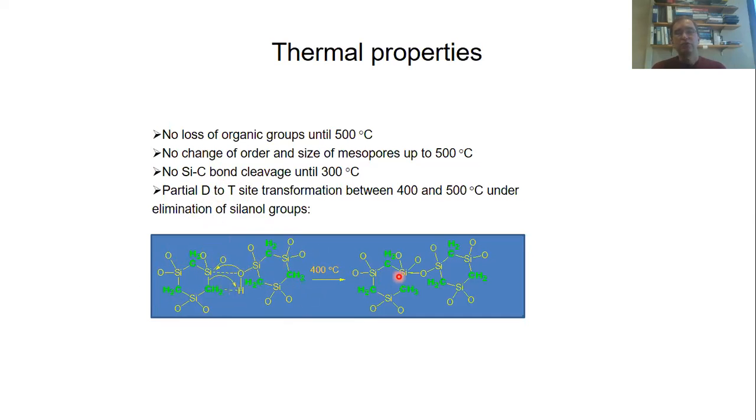So that can actually form a silicon-oxygen-silicon bridge, and it can also form a methyl group. Okay, and these methyl groups are significantly less polarizable than CH2 groups. In addition to that, you have eliminated these polar silanol groups. And by these two effects in combination, you can explain that